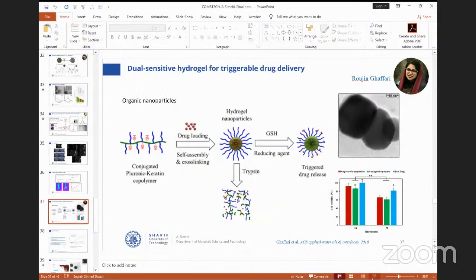The next step was to develop more sophisticated hydrogels, which are dual sensitive. So we wanted to have a hydrogel system, nanocarriers that can release drugs or biomolecules via reaction in the body with some enzymes. We developed organic nanoparticles based on Pluronic-Keratin copolymers, loaded the biomolecules or drug inside, and used self-assembly to create a complex matrix, as you see in the SEM picture on the right-hand side, if it's clear. Hopefully it is clear. The drug is inside.